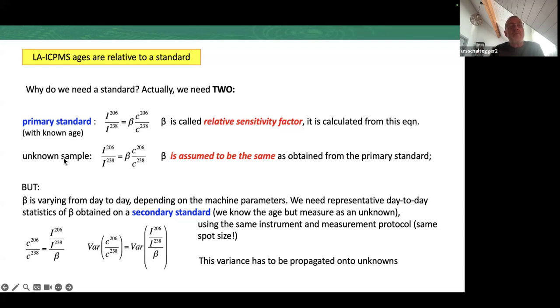So first, we have to control whether our beta is really correct. So we use a secondary standard, from which we also have a very precise and accurate ID-TIMS age. We do the same exercise, but here now we assume that the beta is the same. We just apply this. And very unfortunately, there is some problem with this. The first problem is that the beta is varying within a day or also from day to day, depending on machine parameters and also fluctuations during the day. So what we need is to have a representative day-to-day statistics of beta obtained on our secondary standard.